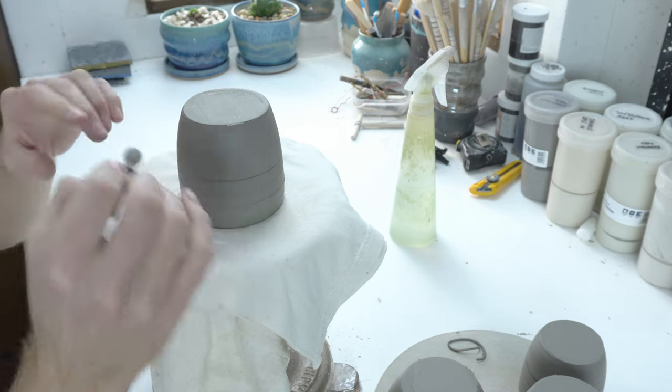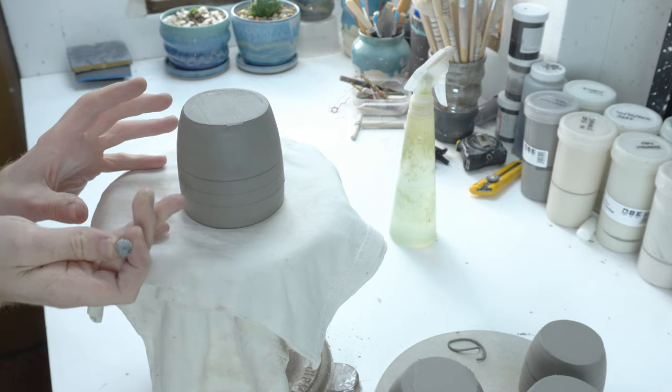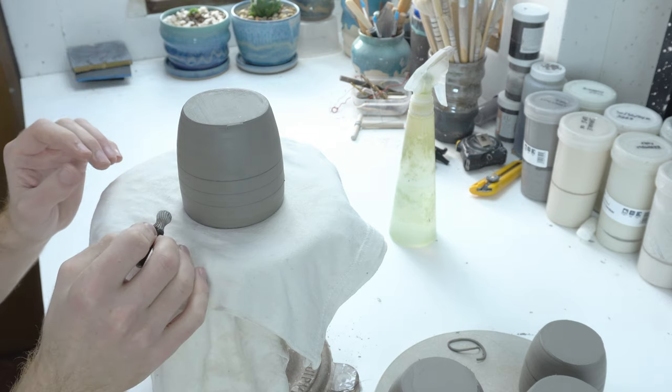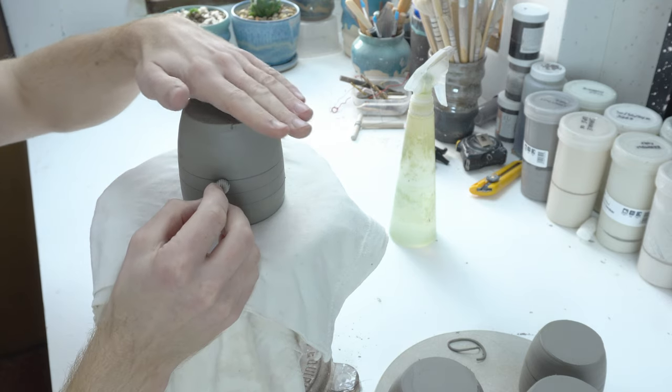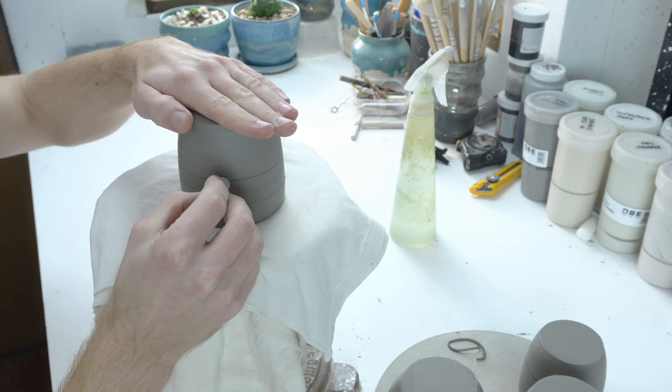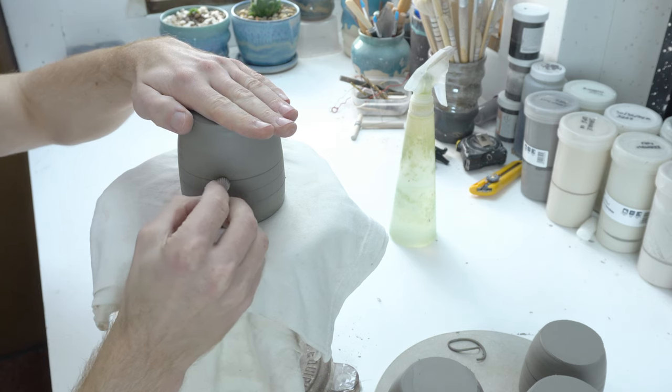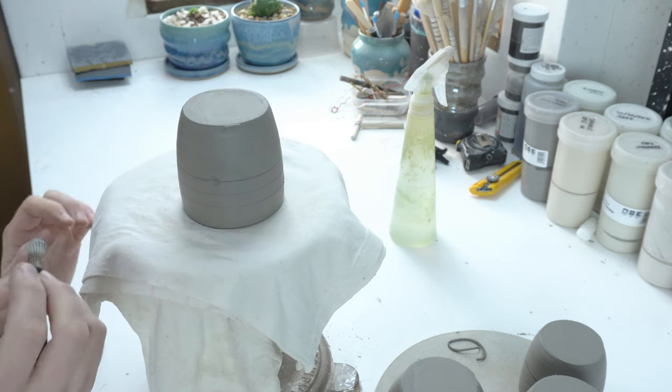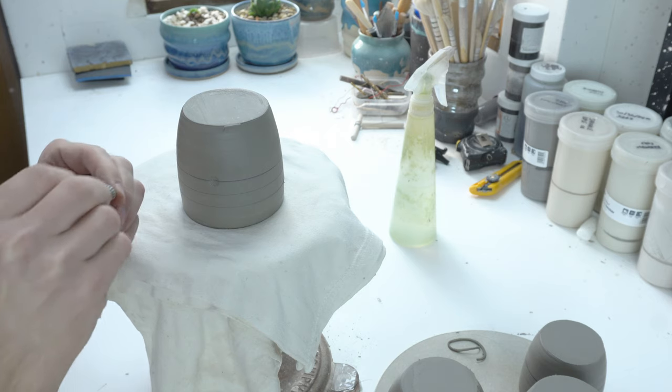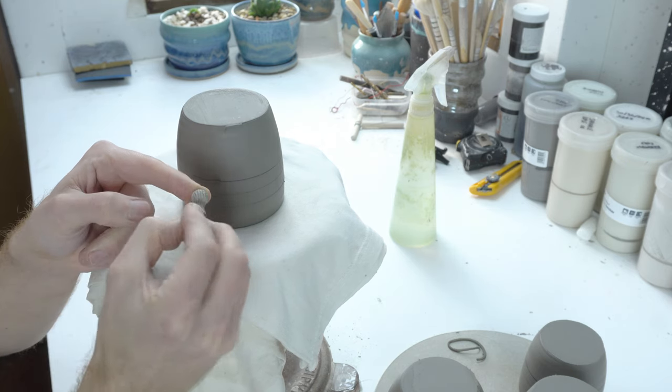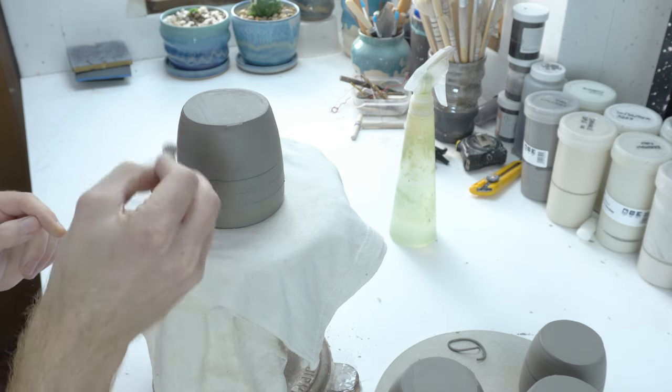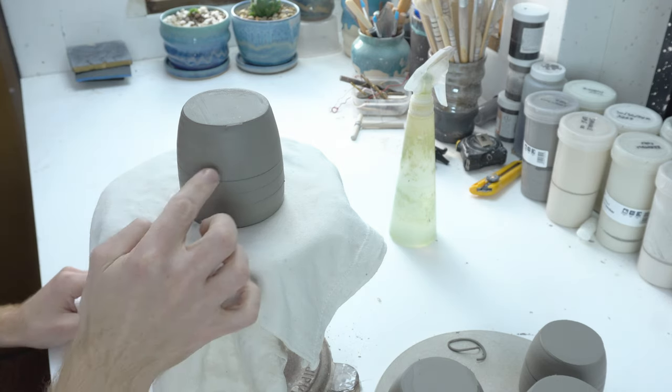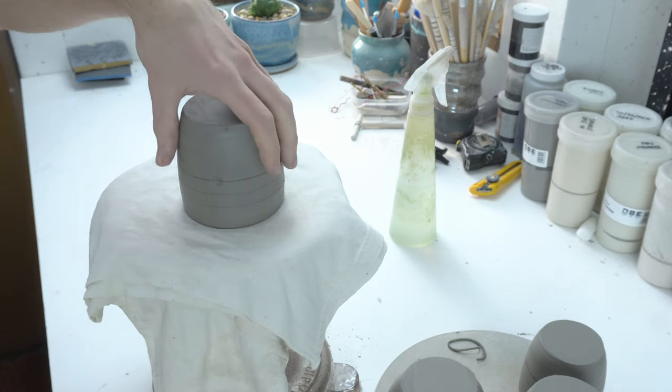If you then apply downward pressure the rim can't deform, which it could do on a slippery surface as you push in. This side will want to slide in. It finds it much harder on a t-shirt or similar soft surface. So push down from the top, line the centre of your bit up with your line, and then roll your hand around. So light pressure. And because each time as you roll it's only applying to the specific point that you're on, you'll find you can bend more clay in that way without deforming the outside.